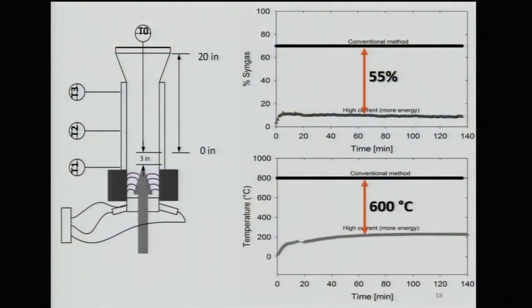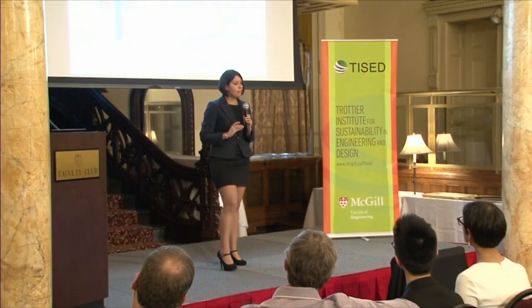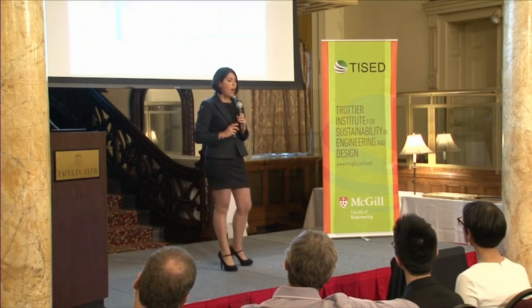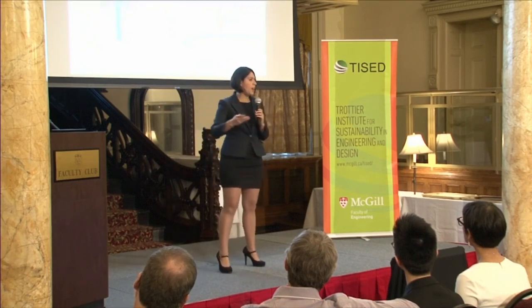If we compare our best result with the conventional method of producing syngas, we see a gap of 55%, but we also see a gap of 600 degrees Celsius in temperature. The question here is, how can we decrease this gap of 55% without decreasing the other gap of 600 degrees Celsius? Meaning, how can we produce more syngas without giving more energy to the process? And this is where the second part of my project comes in.